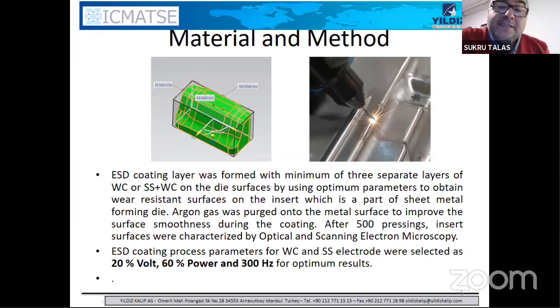The coating, as I said before, has two parameters. Although it says volt here and power, power is more important than the voltage. Power is directly related to current, the amount of electrons you transfer from one electrode to another. Another parameter is frequency. In this case, we used 300 hertz. It can go up to 1500 hertz, 1.5 kilohertz. Afterward, it doesn't mean anything. You can go down to very low frequency as well, like 100 hertz. But what we found in this research is that 300 hertz is enough for us.